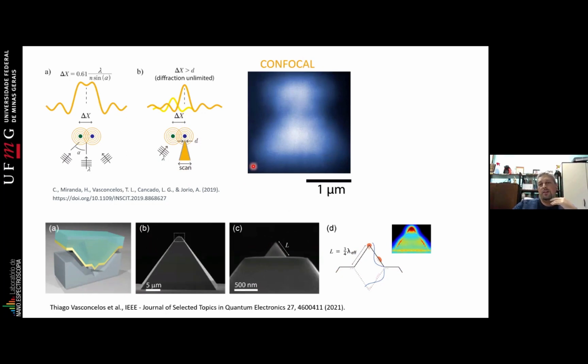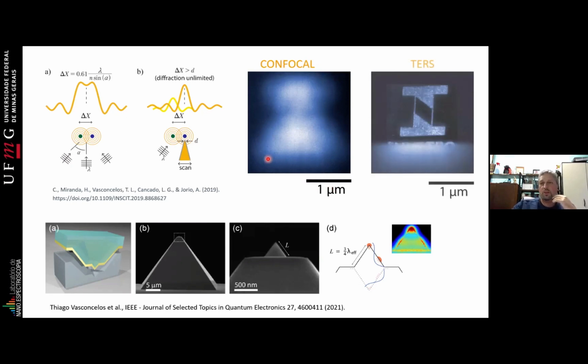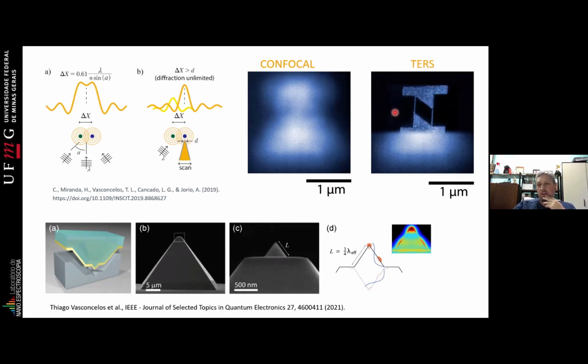This is just an example. This is the confocal image of graphene, where people at Inmetro made the Inmetro logo with ion bombardment. For those who don't know, Inmetro is our standards bureau, like NIST or NPL. They made the logo with defective graphene, and we measured the confocal Raman of the logo. Because it is so small, we don't have the optical spatial resolution to see the logo, but with the tip-enhanced measurement, we can see the logo nicely. This is the gain in optical resolution.